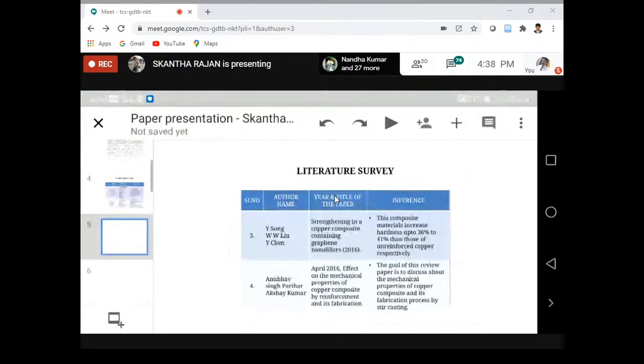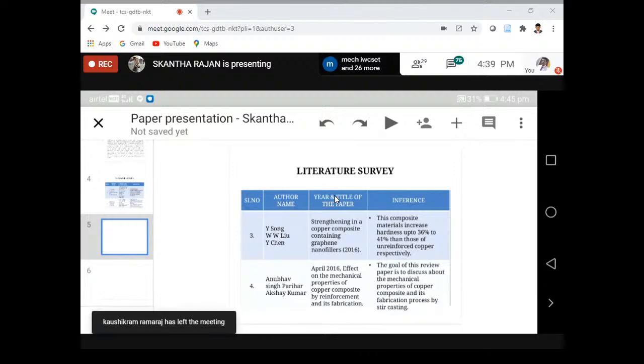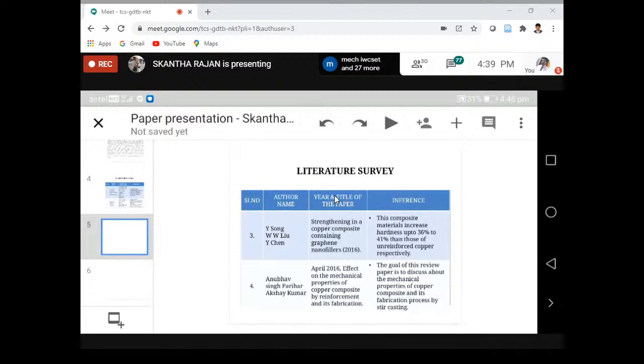So next. This literature survey is on strengthening a copper composite containing graphene nanofillers. Here, they use graphene nanofillers as the reinforcement. This composite material increases the hardness by 30% to 41% compared to unreinforced copper. Unreinforced copper means the copper which is in pure form, where no reinforcements are added. When graphene nanofillers are added as a reinforcement with copper, it will increase the hardness by 30 to 41%.